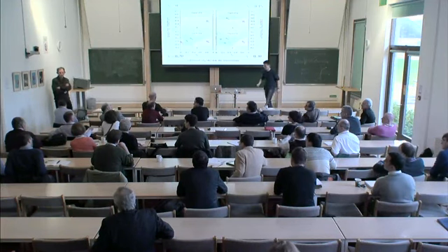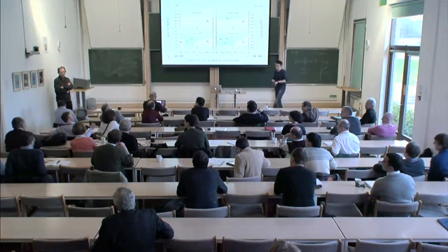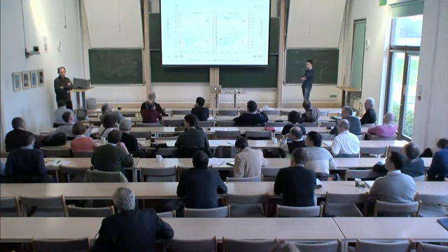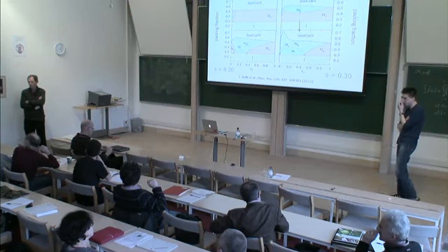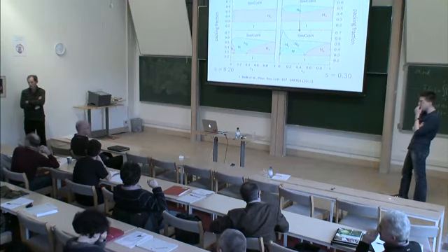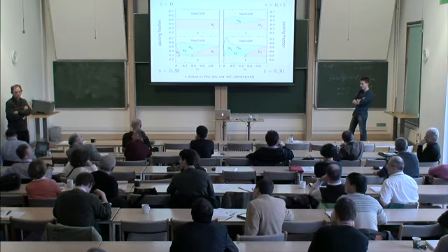Simone, the depletion picture is very nice. In the spherical case, as you know, if you have non-interacting depletants, then for size ratios, the ratio of the size of the big ones to the small ones, the mapping to a one-component system becomes exact when that size ratio is less than 0.154. Do you have analogous results in your case?